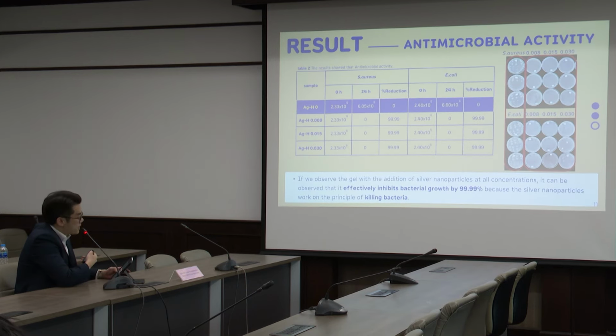So the antimicrobial activities. This image shows the colonies in the first column, which refers to 0 phr. The colonies refer to alive bacteria, and the other plates do not show any colonies. As you see in this table, in the first row, the gel without silver nanoparticles, in both Gram-positive S. aureus and Gram-negative E. coli, after 24 hours, an increase in the number of cells was present.